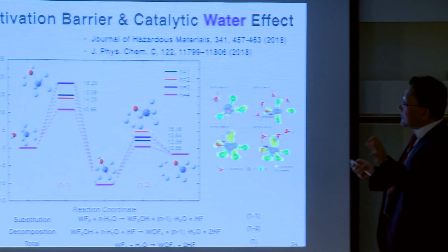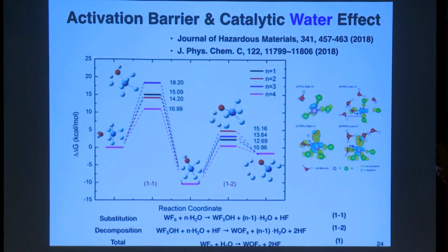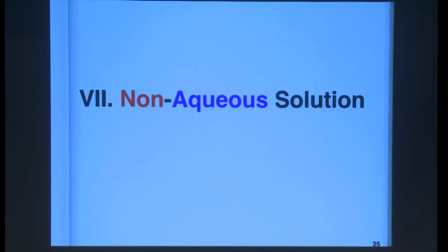But how about predicting reaction velocity? Then you have to calculate the energy barrier. You can calculate it. We can apply nudged elastic band (NEB) calculations, and you can capture the activation barrier for a certain reaction from one chemical to another. Very well captured. So all this formalism can be a computational framework to predict, discover or design certain materials. You can incorporate all this methodology into one computational framework.